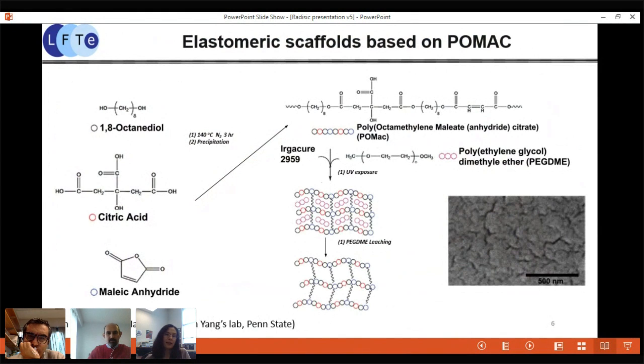And about 10 years ago, we came across this wonderful paper that Jian Yang published in Soft Matter, and it describes synthesis of POMAC using 1,8-octanediol, citric acid, and maleic anhydride through a very simple one-step single pot synthesis. And this reaction leads to a polymer that can be elastomeric and that cross-links both in response to UV exposure and in response to heat.